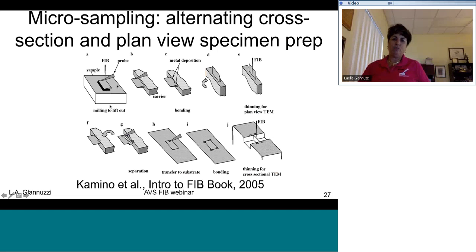This Hitachi group has shown that after doing this plan view section, you can then cross-section a plan view of the same area. So after you FIB mill and do your TEM analysis, you can put it back in the FIB, attach the probe to the sample and cut it free, attach it to a substrate like silicon, and then cross-section the same area that you just looked at in plan view, and throw that in the TEM, and they've shown that you can actually do this 10 more times. You can do a cross-section of the plan view, and you can do another cross-section of the cross-section of the plan view. So pretty cool stuff.